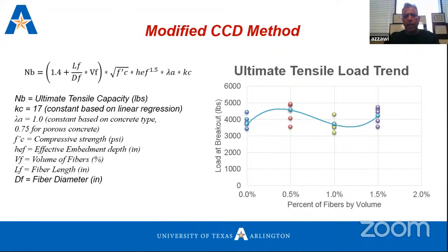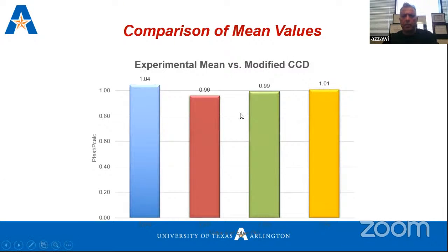After that, we take the ACI code and the equation and try to modify it by applying a term here, covering adding the fibers itself. So we provide this term here, LF by DF by the steel, by the polypropylene fiber ratio, and try to check this formula and validate it with the experiment results. So this trend shows us the results for using the modified CCD method, which is proposed by the ACI code. This is the comparison between the modified CCD method and the experiment. So we have a close agreement between both methods.